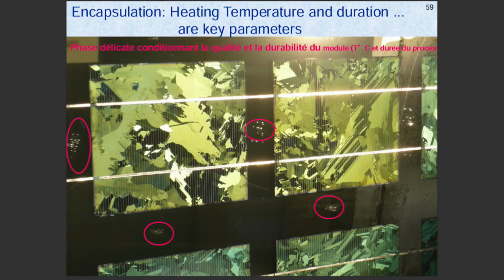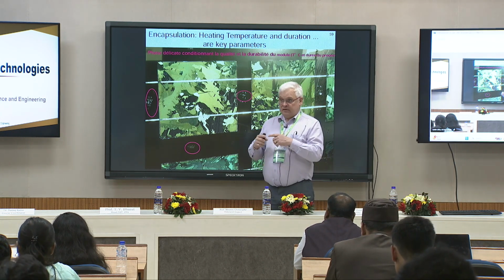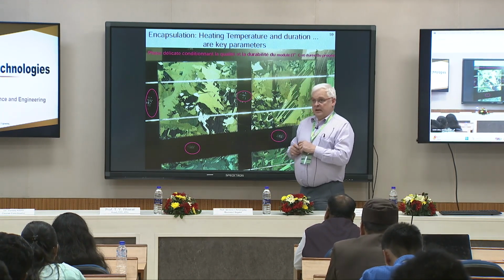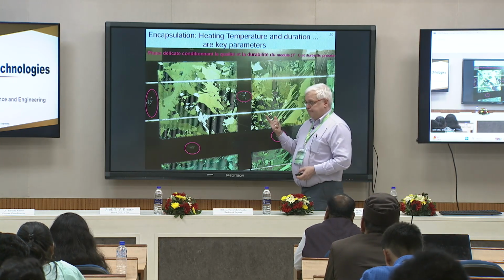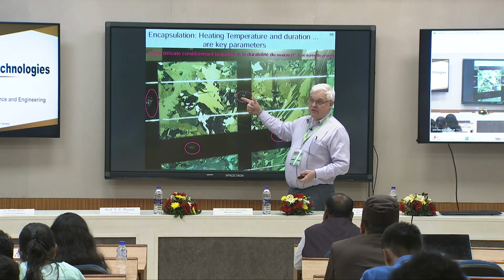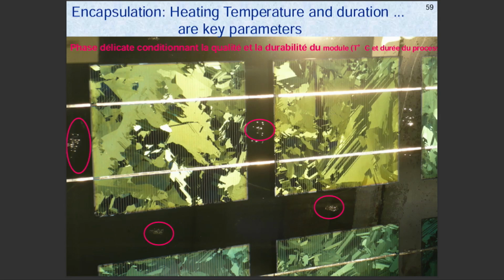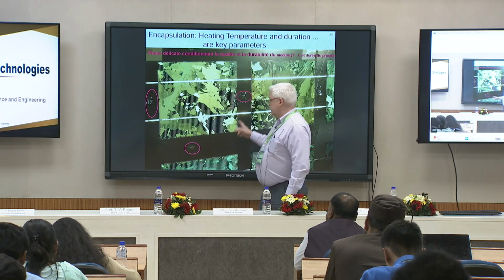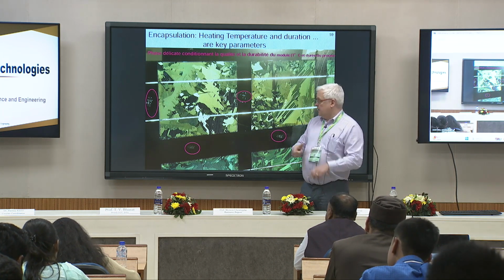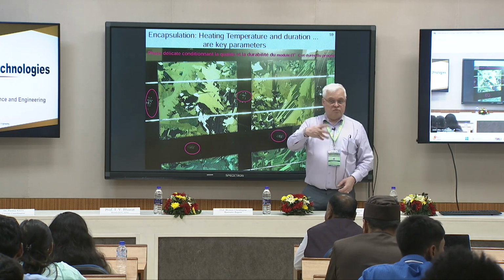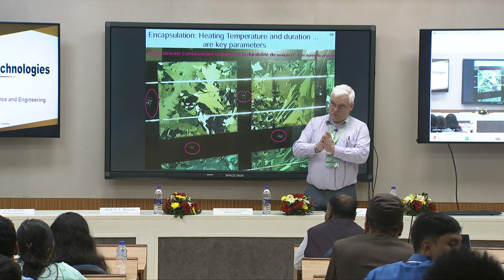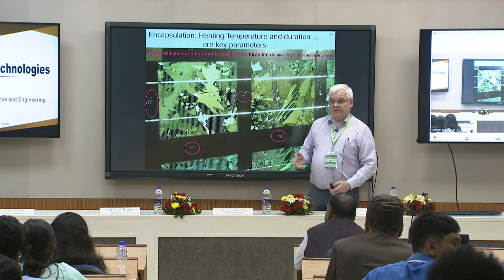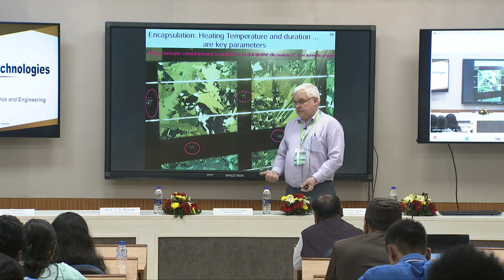But what is very important is the temperature. The manufacturer never gives the temperature. They heat the panels in order for the resin to melt. And the time, okay? Temperature and time are two very important parameters. They are important because they condition the future evolution of the PV panels. You can have panels that look the same when they are manufactured, but over time they will age differently if these parameters are not optimized. You will see some bubbles that will appear after 2 years, for example. You can have delamination. I will show you some pictures. The resin delaminates, whereas when they are just manufactured, you don't see anything. So, a very important parameter.